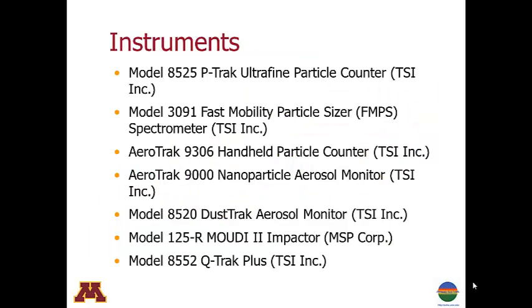These instruments included a P-Trak ultrafine particle counter that measures number concentrations for particles with diameters ranging from about 20 nanometers up to about 1 micrometer or 1,000 nanometers. We used a fast mobility particle sizer, or FMPS, to measure the size distribution by number of particles ranging from 5.6 nanometers up to about 560 nanometers. We used a handheld optical particle counter to measure larger particles, those ranging from about 0.3 micrometers or 300 nanometers up to about 10 micrometers in diameter.